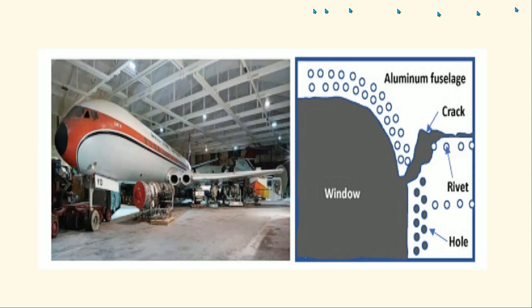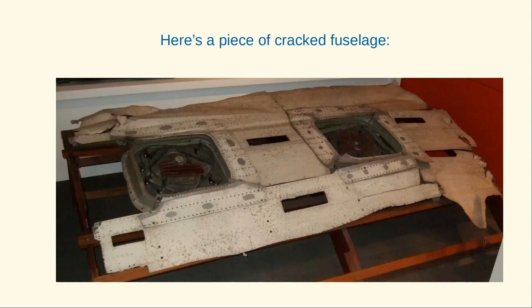So here's a diagram of an aluminium fuselage, rivet holes, and that's the sort of area the crack formed and spread. And of course, if a crack forms and then extends, that means eventual failure will happen. And here's a piece of the cracked fuselage recovered afterwards, and you can see here, for example, that we've got a crack growing from the relatively sharp corners of the window, similarly here. And that happened because the designers didn't appreciate the effects on stress concentration of sharp corners.